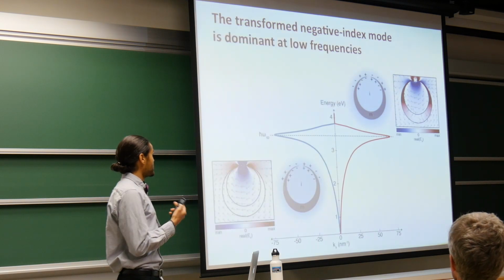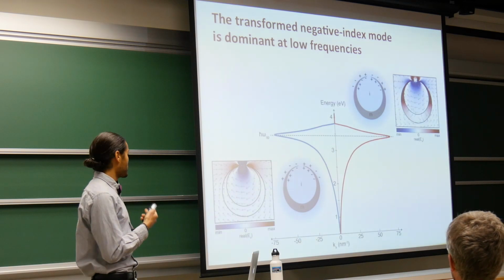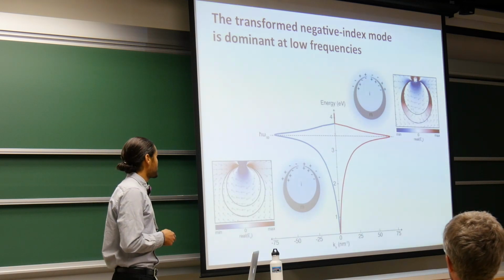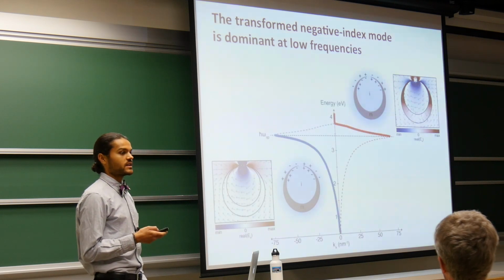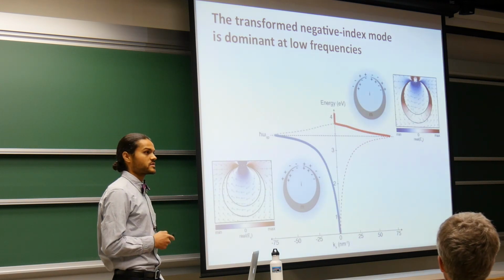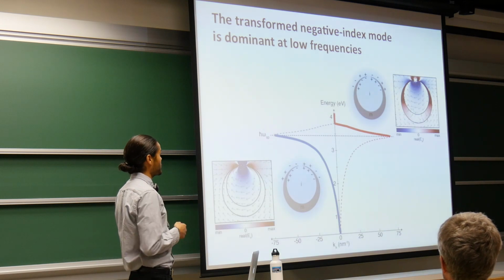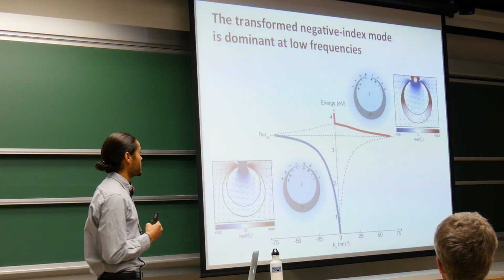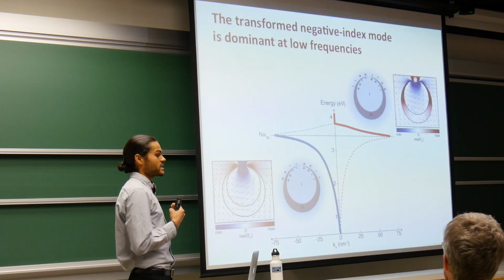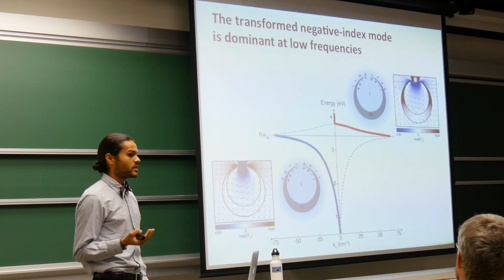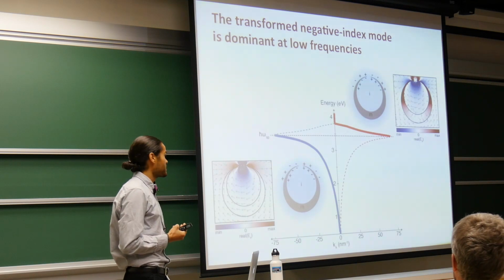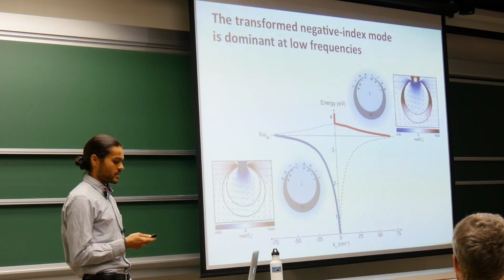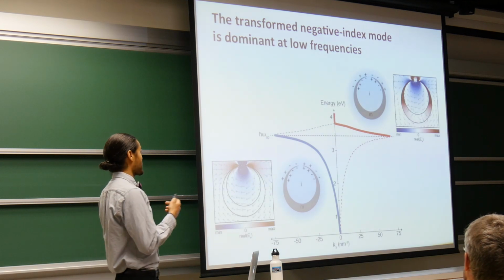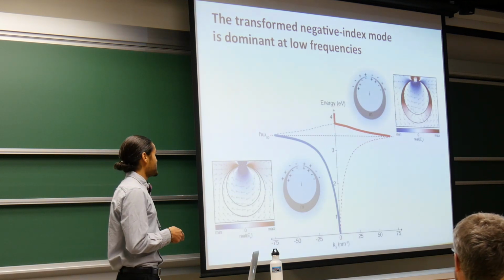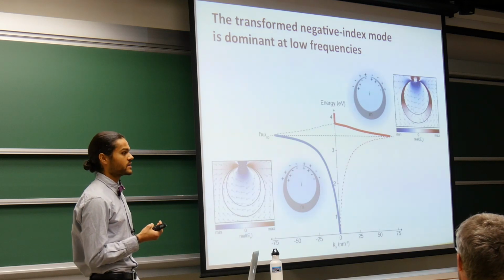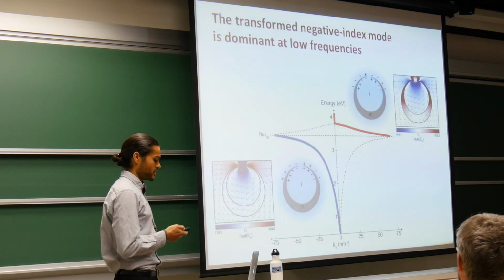When we investigate the differences between these modes, we find that the negative index transformed mode, shown on the bottom left here, is actually the one that's excited for all frequencies below this surface plasmon resonance frequency. And the other mode is only excited for the frequencies above the surface plasmon resonance. So in essence, we've transformed the negative index waveguide mode into a degenerate electric and magnetic dipolar response of this finite meta-atom. One of the caveats of this particular transformation is that, as I mentioned, the tips are actually singular points, which is, of course, not realistic for any real device.